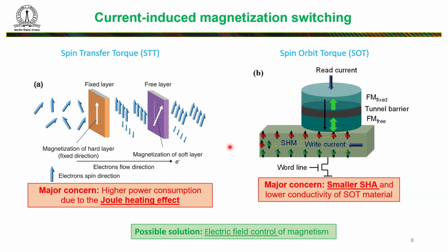One of the very well explored ones is spin orbit torque, where you flow the current through a heavy metal. Then, due to the spin Hall effect, this charge current can be converted into spin current, and the spin current can actually switch the ferromagnetic layer, which is just adjacent to your heavy metal, and that way you can also switch the resistance state of this MTJ device. But we need a material which shows a very high spin Hall angle, and at the same time we need a material which shows very good conductivity, so that you flow a decent amount of current and you can actually achieve what you want to achieve. But so far we don't have such a magic material yet, which can lead to a robust technology.